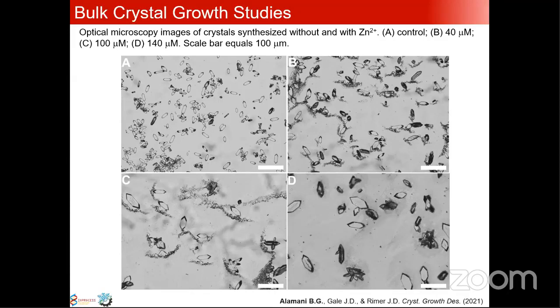As you can see, you have fewer and fewer crystals growing, and at the same time larger and larger crystals. Interestingly, at some point you will see large intergrowth forming, which has been presented in the literature as a potential precursor of other, bigger types of stone, which becomes a medical concern. So we started to concentrate on this interesting morphology.